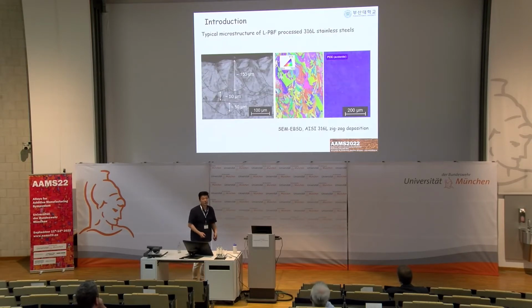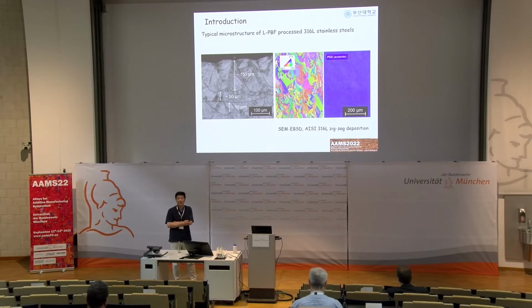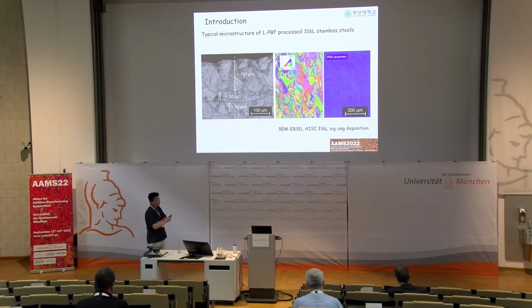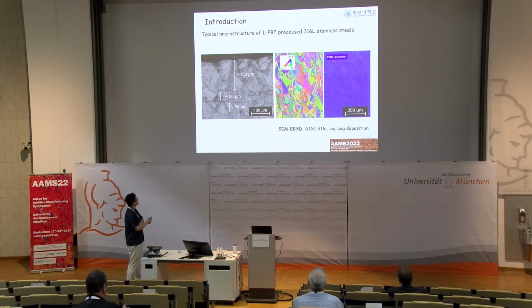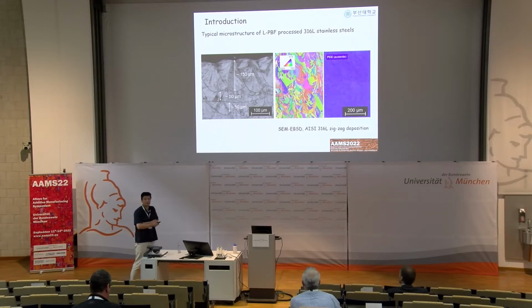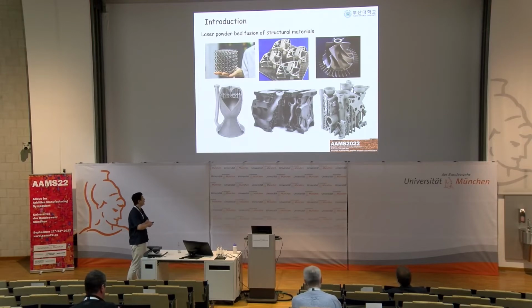Our main question was, indeed, do we have any strong size effect in the powder bed fused 316 stainless steel alloy? This is the typical microstructure from our LPBF facility. Probably the microstructure is pretty much the same for every kind of laser powder bed fusion process of this material. We have laser beads and some unique microstructure and grain structure, which is normally characterized as fine grains with some texture. But we always consider this material as a homogeneous one.